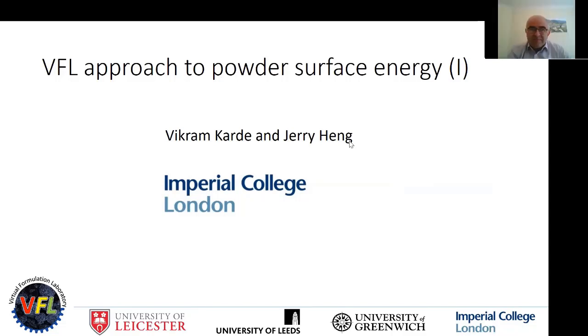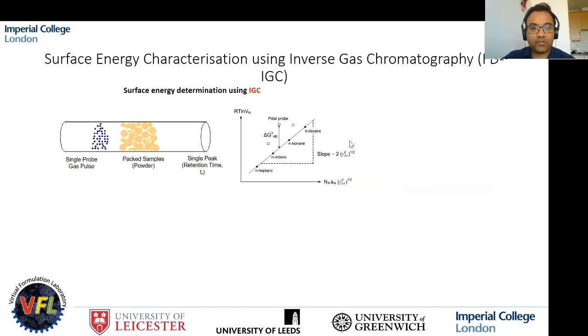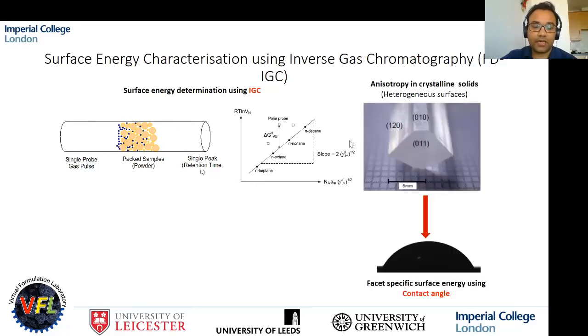Very good. Yeah, thanks. So at Imperial, we are working on surface energy characterization of particulate solids. We believe surfaces are very important as they control interactions like solid-solid, solid vapor, and solid-liquid. Here we are defining surface energy in terms of thermodynamic sense, which is free energy change per unit area at constant temperature and pressure. Now, there are different techniques to measure surface energy of solids. Here we have used a technique called inverse gas chromatography, which is IGC. It is the reverse of traditional chromatographic technique. So we have an unknown sample packed in a glass column, and we pass known vapor probes, and we determine the interactions of these vapor probes to calculate the surface energy.